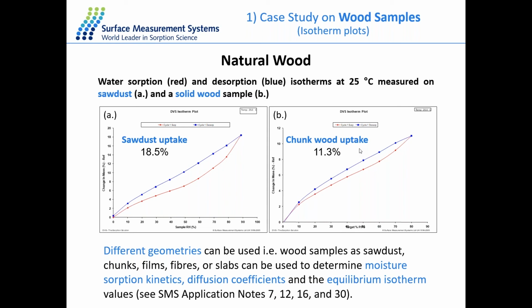So the sawdust sample with the uptake around 18% is much higher than the solid wood sample at around 11%. And the sawdust sample also has a wider hysteresis gap between the sorption and desorption isotherm. That means there is more water diffusion happening in the sawdust sample, resulting in a higher degree of bulk sorption. So with the DVS technique, we can easily characterize this kind of behavior of the wood, that different geometry of the sample or different particle size may affect the diffusion behavior or the sorption kinetics, as well as the equilibrium uptake for the wood samples.